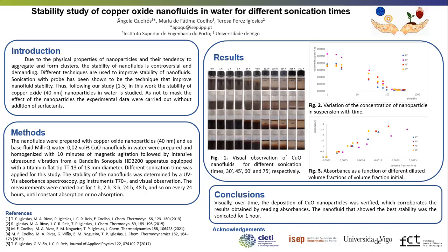Thus, following our study, in this work, the stability of copper oxide (CuO), 40 nanometer nanoparticles in water is studied. So as not to mask the effect of the nanoparticles, the experimental data were obtained without the addition of surfactants. The nanofluids were prepared with copper oxide nanoparticles and milli-Q water as the base fluid.